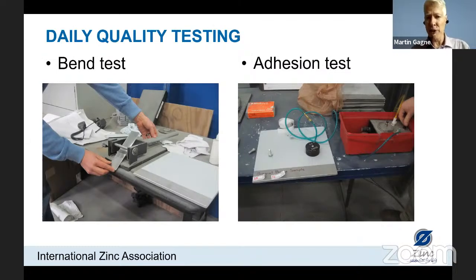On the right-hand side, we see the adhesion test. And actually, we're doing the adhesion test, but we've also done a surface preparation test on these panels. So we can see it's a much thicker, large, square panel of steel. This was abrasive blasted, and then they did a tape test, and we can see the two tapes that have been applied to this panel. That front end of the panel is masked, and then we spray the zinc onto the surface. Now we will do the pull-off test on the zinc.